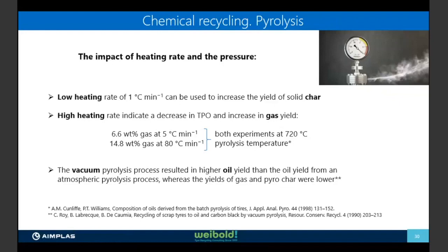And at 80 degrees per minute, you can achieve close to 15% of gas. And the vacuum pyrolysis process resulted in higher oil yield than the oil yield from an atmospheric pyrolysis process. And in this case, in vacuum, the yields of gas and pyrochar were lower.